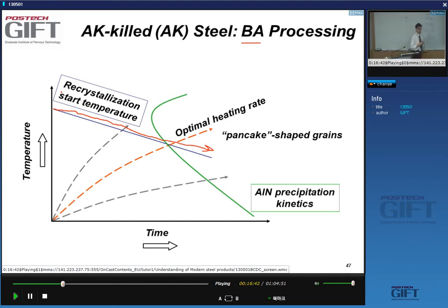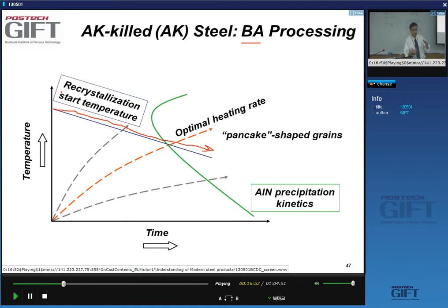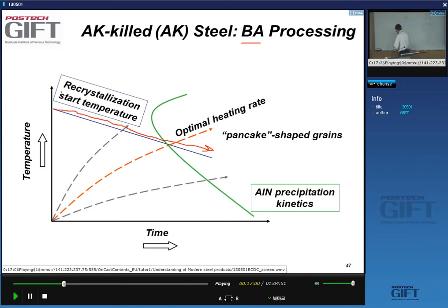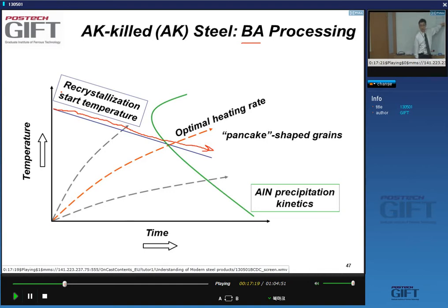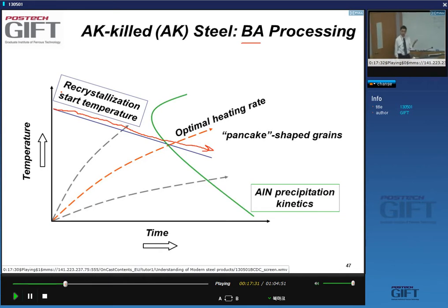So you keep aluminum and nitrogen in solution. However, in ferrite, the solubility of aluminum nitride is very low. As soon as we have enough temperature, aluminum nitride will form. The precipitation kinetics look like a C-curve. Why? Because at very low temperatures you have little diffusion so precipitates cannot form and grow, and at very high temperatures the solubility is higher so the kinetics of formation of aluminum nitride are lower.